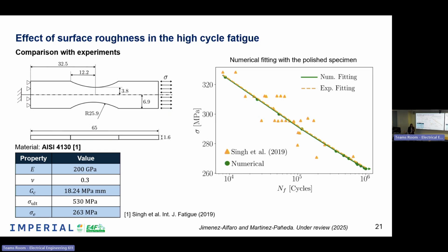And first of all, we need to define the parameters of our model. As I've shown you before, when we were presenting the phase field model, we have different parameters, so we need to define them and to be sure that this works. So we use just the polished specimen with no roughness at this stage, and we compute our parameters. We use the phase field to check that our numerical fitting is fitting the experimental one. So we approach just the experimental results of the polished specimen. Once we have our numerical calculations completely calibrated, then we go on with the surface roughness.